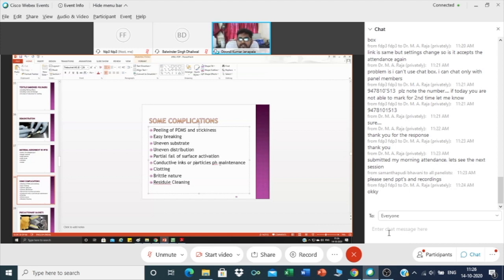Conductive inks or particles, pH maintenance. So if you use something, you leave it for some days, then the nanoparticles will group together, and when you directly put it into the spray coating or something, it will clot. So the clotting problem you need to address. Make sure that the pH is maintained. Brittle nature: if you are adding too much oxide into your polymer, the polymer will become brittle and it will break easily.